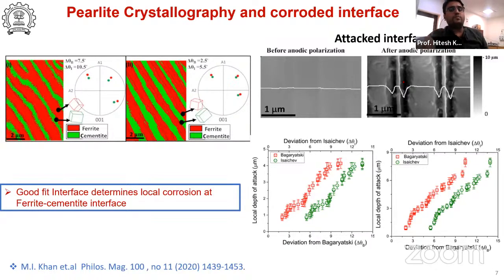Interface is basically going to play an important role here. So what we did, we calculated the Isaichev and Bagaryatski relationship with these colonies. Isaichev and Bagaryatski is basically the interface relation between ferrite and the cementite. As the material is nearer to the Isaichev and Bagaryatski interface crystallography, the material is more intact, and we can see the deviation from Isaichev and Bagaryatski is increasing.